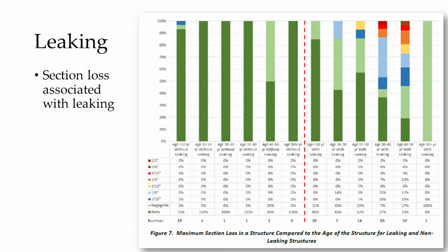These are section loss. So that yellow is 3/16, quarter inch for the orange. The dark brown at the top on the right is 3/8. They show a half on the scale, but they didn't get anything as much as a half. So as the bridge gets older, if it's leaking, they start to see section loss. There is one bridge over 50 that's doing well, but it is just one bridge.